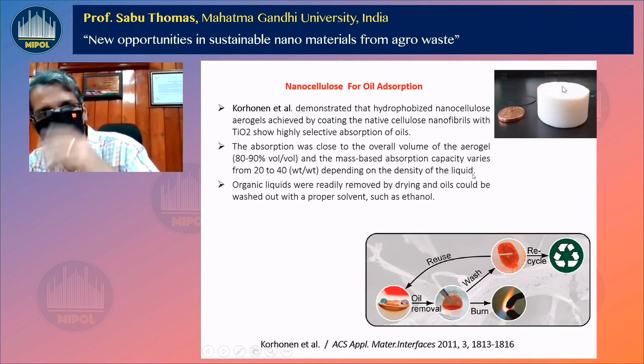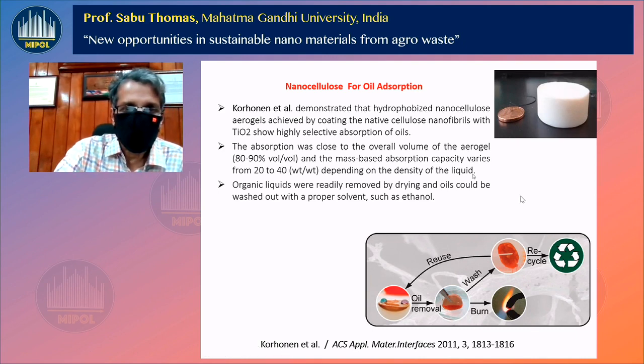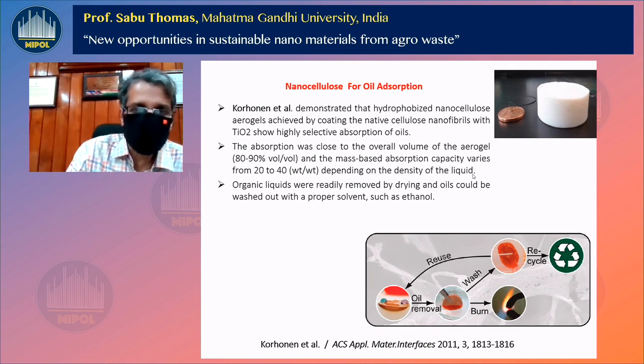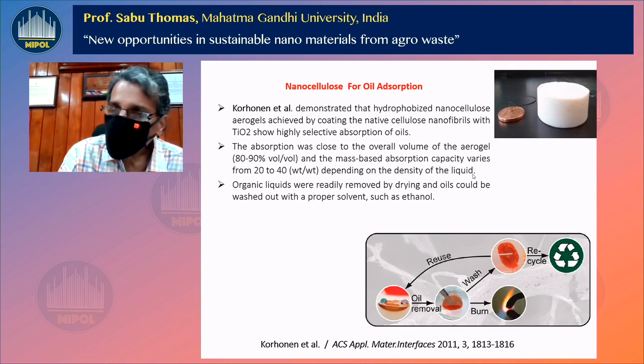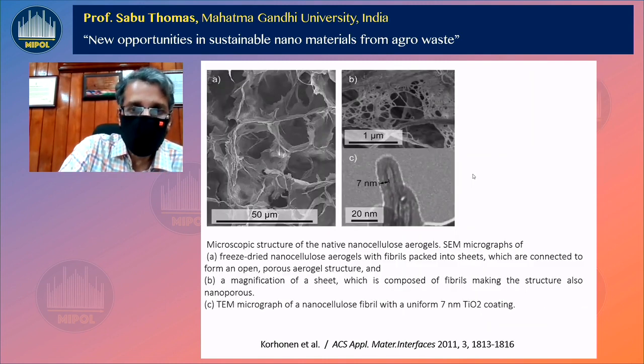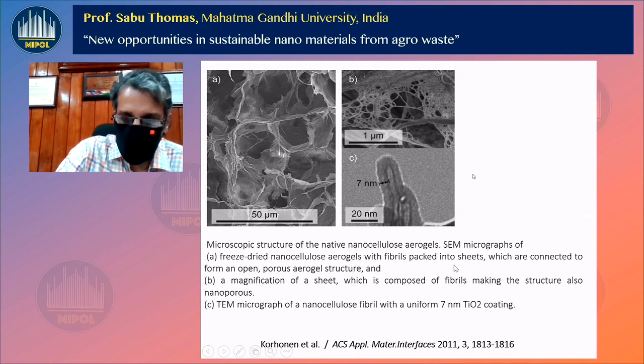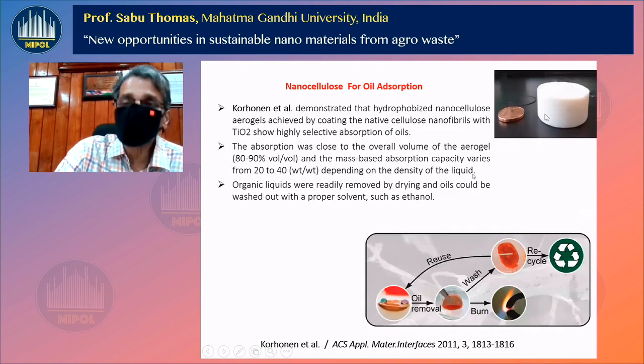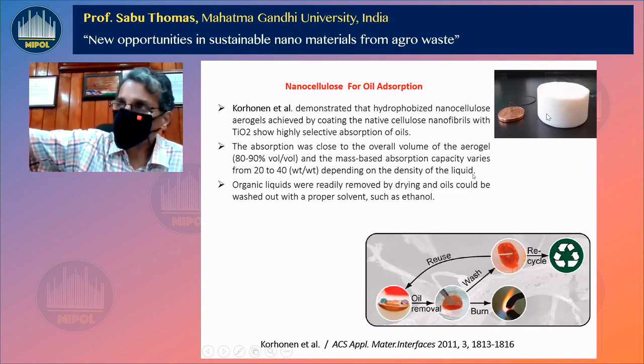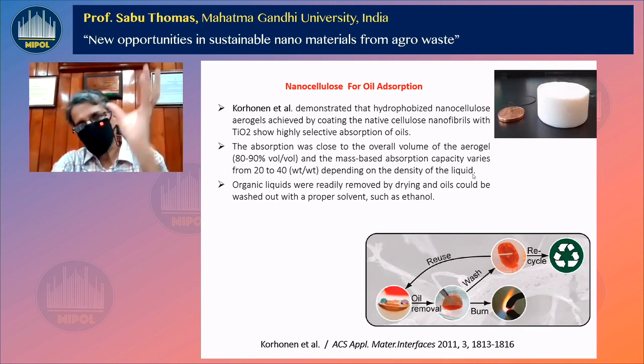Manufacturing of aerogel is quite simple. And then they made aerogel. And then the surface of aerogel has been made hydrophobic. How would they do hydrophobic property? They gave a coating with titanium dioxide. Look at this. They made aerogel by freeze drying. And then after freeze drying, they gave a coating with titanium dioxide. So this aerogel became highly hydrophobic. Doesn't like water because it is coated.